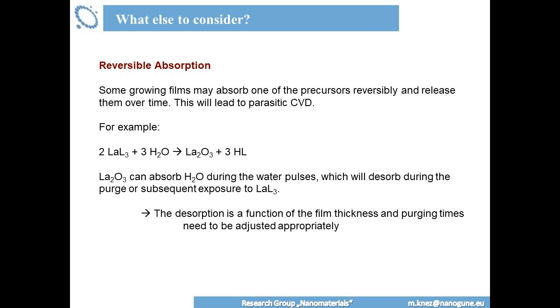Okay, you have also to consider in those structures reversible absorption. So you have some films, and I think yesterday, again, I think it was Nico talking about the ruthenium. It's a very similar case. You have films which absorb part of the precursor, and they release them during the next cycle. So you have a parasitic CVD happening while releasing the absorbed precursor. Not adsorbed, but absorbed precursor. It happens here, it happens also with the ruthenium. The oxygen is then released during the next cycle, which leads a little bit to a modified chemistry there, and it's not a pure ALD process in some cases.